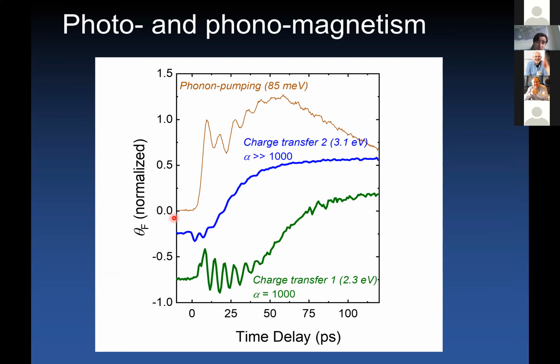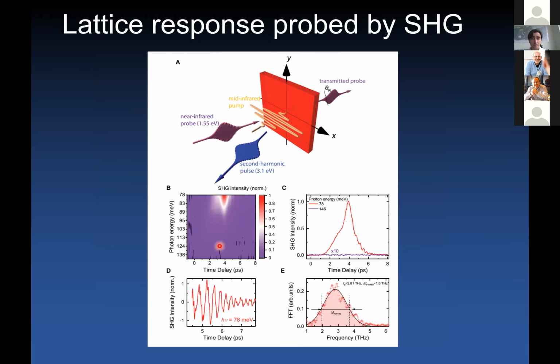Instead, when you excite the structural degrees of freedom, so you're resonant with a phonon pumping, then your magnetization itself develops within the first precession of your spins. So within a few picoseconds, you have developed your magnetization. So an improvement of two orders of magnitude in the speed of your phase transition. This highlights the more efficient character of phonon pumping with respect to conventional charge excitations.